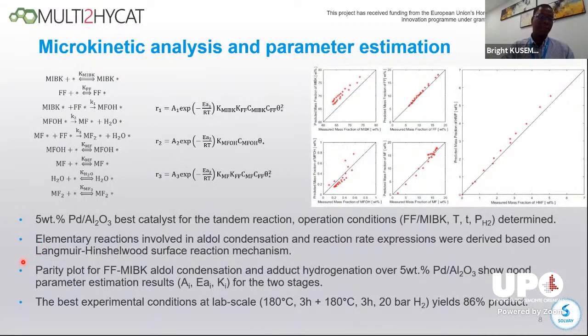And the parity plots for furfural and MIBK aldol condensation, as well as the subsequent hydrogenation conducted using the palladium on alumina catalyst, showed a good parameter estimation between the measured values and the predicted values obtained using the model. And this involved both steps, the aldol condensation as well as the hydrogenation. And from this microkinetic analysis, the best experimental conditions were obtained, and they were subsequently used for further cost estimation assessment, which I will show in the next slide.